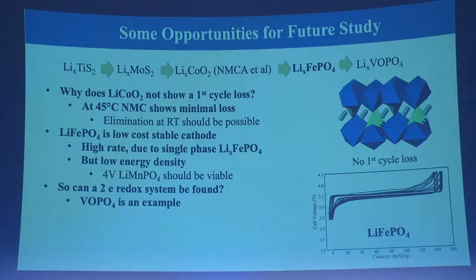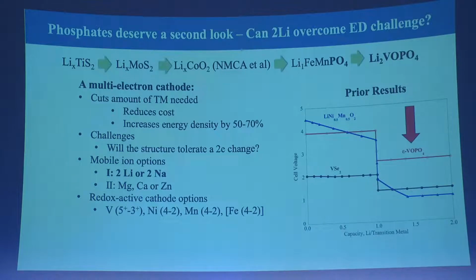So we looked at this and said, no, this is great, it's stable, it should be used in grid storage. It is a little bit, but nowhere near as much. No nickel, no cobalt, should be very low cost. Iron is free, phosphates, tons of it around. So we said, let's see if we can increase the energy density by putting more than one lithium in. And there was some prior work we had done and others had done. We initially looked at the layered sulfides and selenides, and it turns out vanadium diselenide, you can put two lithiums in. You can see the red, the plot at the bottom here, this one here.